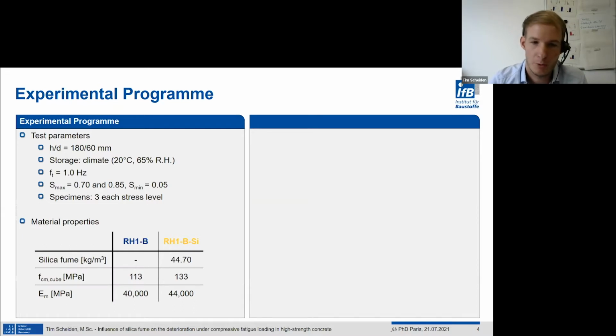In the first step, both concrete mixtures, which differ in the addition of silica fume, were characterized. So here we have the RH1B, the reference high-strength concrete without silica fume, which is the reference high-strength concrete in the priority program SPP 2020. And the concrete with silica fume, here in yellow, which is a variation of the reference composition. As expected, the compressive strength increases, which is congruent with the literature, and the modulus of elasticity also increases.